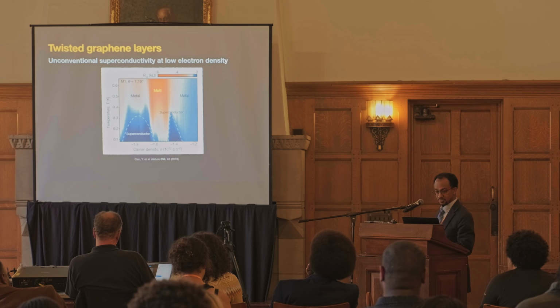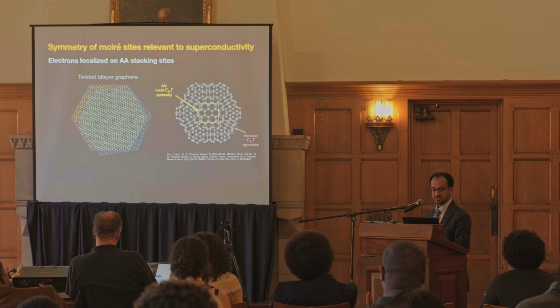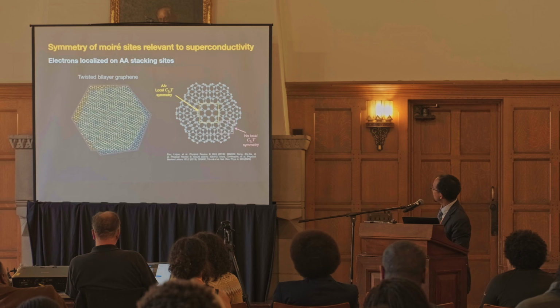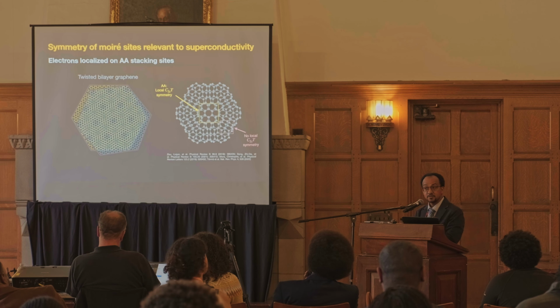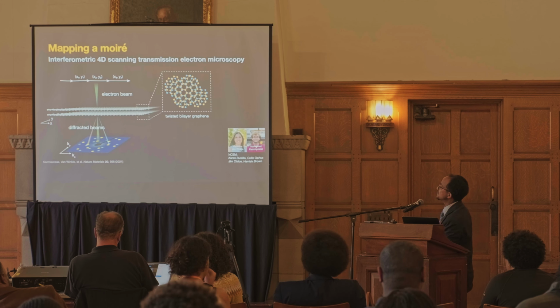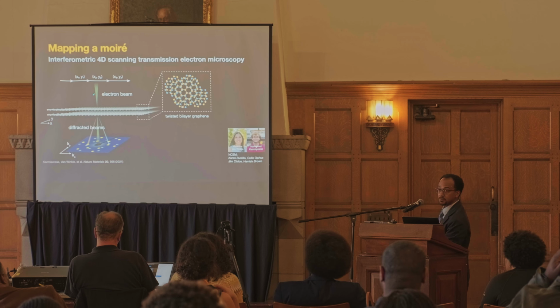So I showed this cartoon with the twisting and so on, that sort of animation over here. And what we wanted to know is, is this structure realistic? Is that the real structure of this superconducting material? So the experiment we did is we used electron microscopy.